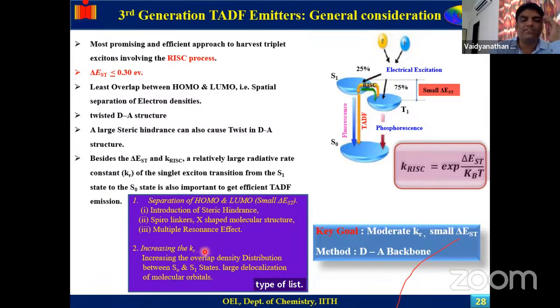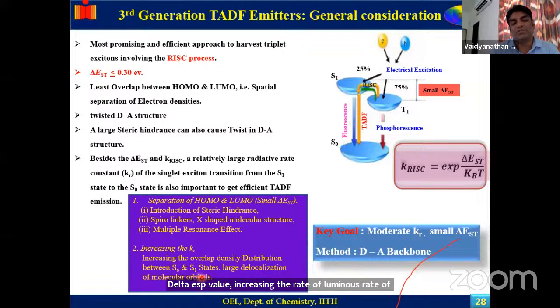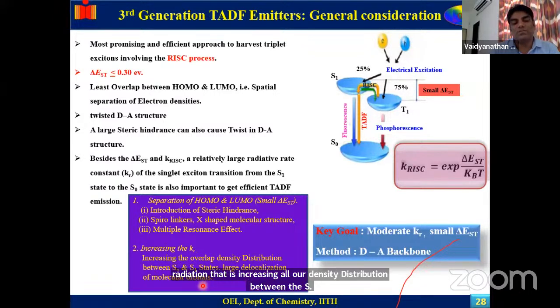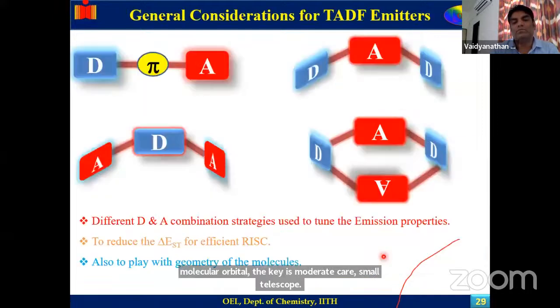Increasing the rate of luminescence, the rate of radiation, means increasing the overlap density distribution between the S0 and S1 state, with large delocalization of molecular orbital. The key is moderate kr and small delta EST. The method is to use a donor-acceptor backbone.